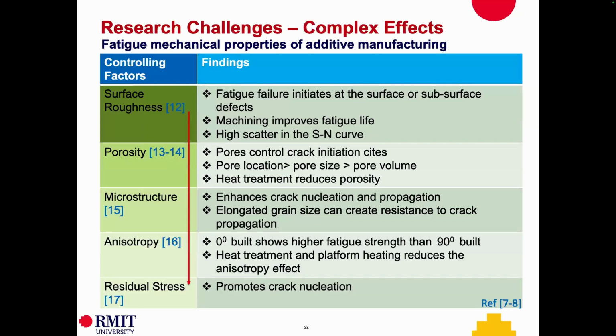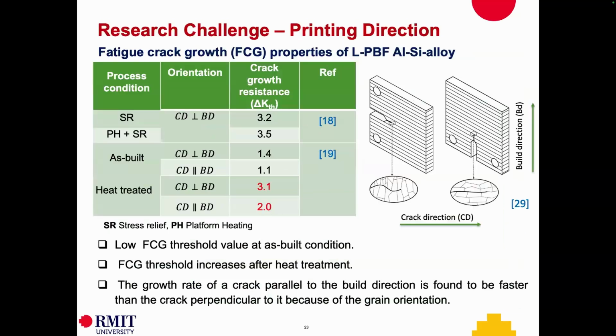For surface roughness, failure initiates at the surface or subsurface. If we do machining, we can improve fatigue life, but one problem is higher scatter, which we talk about in the rest of the presentation. Porosity controls the crack initiation size, but it has a marginal effect, as you will see later. Out of the three things, a given pore's location, size, and pore volume, the location has a greater effect than pore size and the pore volume. We tend to think a larger pore will significantly reduce fatigue life.